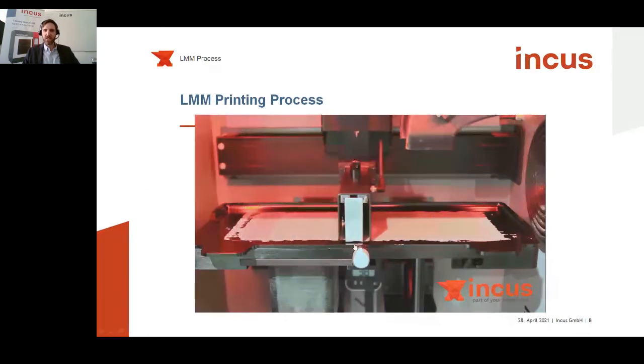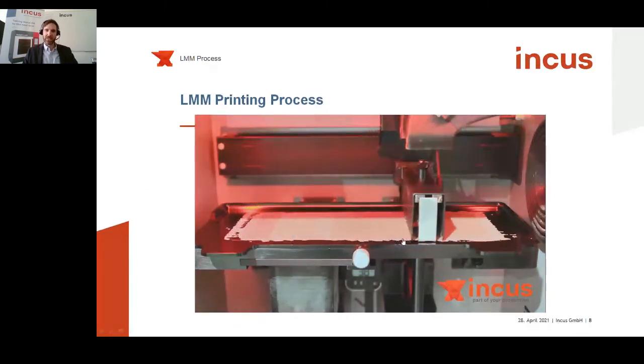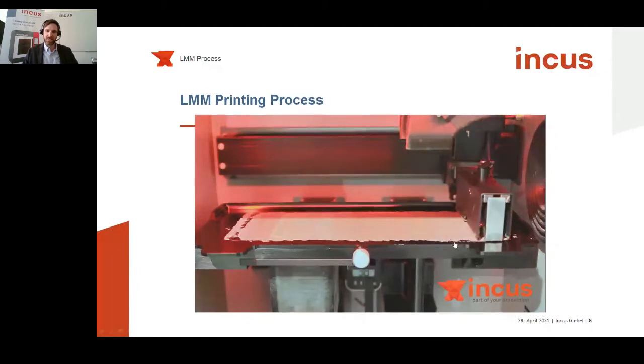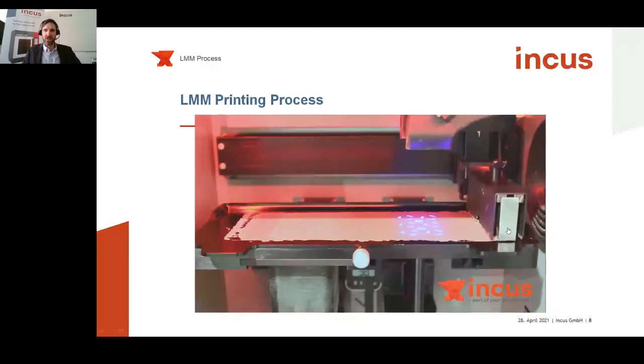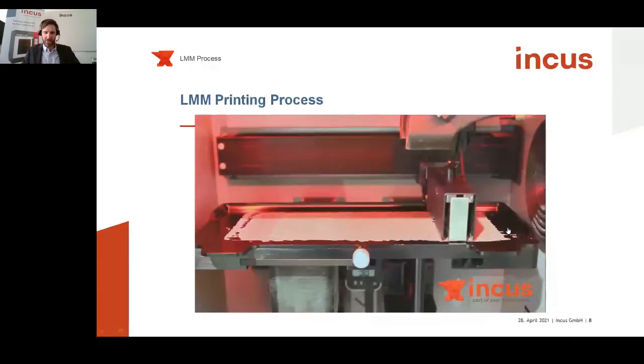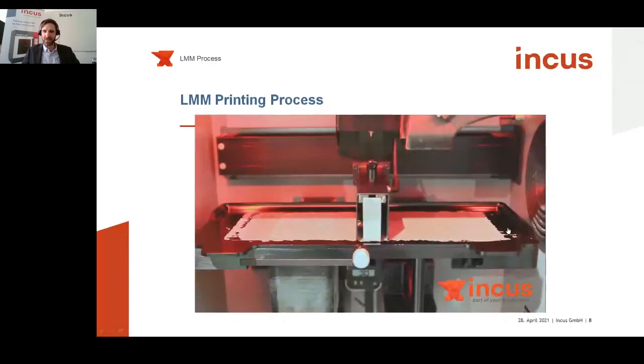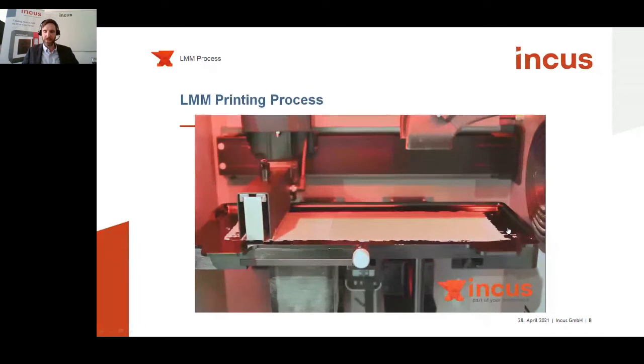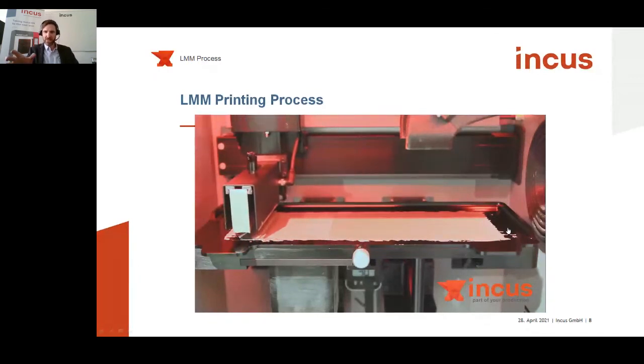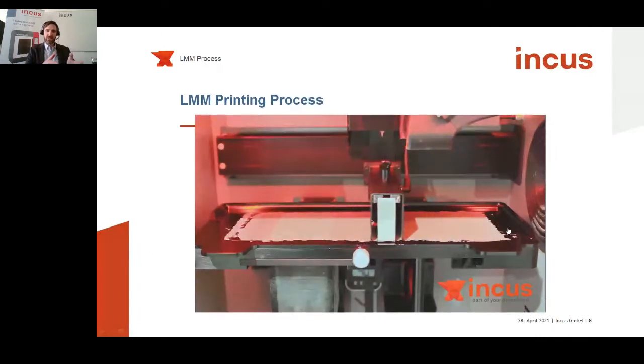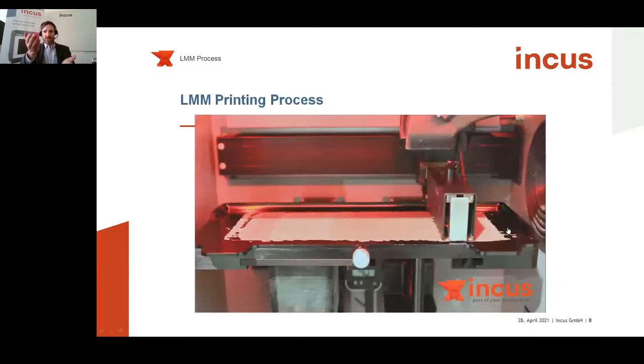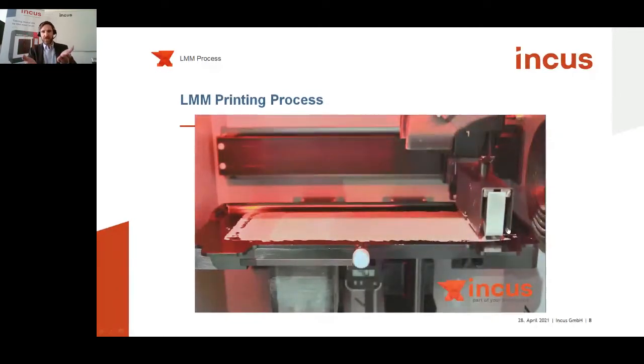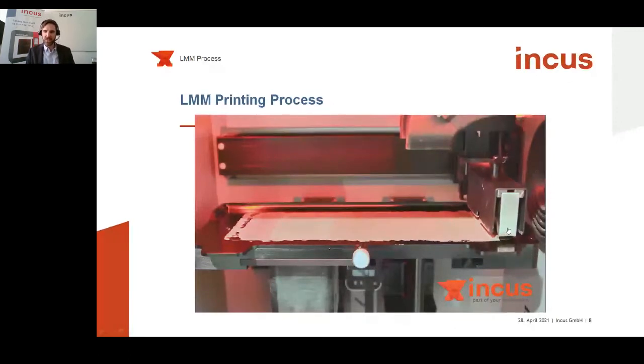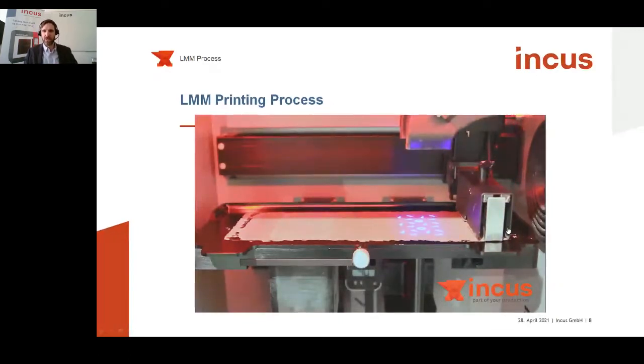So here is the recoating of a new layer of material. In this case, we print stainless steel with a layer thickness of 20 microns. And after the coating process, you see the polymerization with blue light. And yeah, the printing process doesn't get more exciting than that. This is how it looks layer by layer. And on the right side is the set stage, so the printing stage, which moves down layer by layer. And on the left side, you see the material piston. So as the set stage moves down, the material piston adds material to the printing process. So we never run out of printing material.